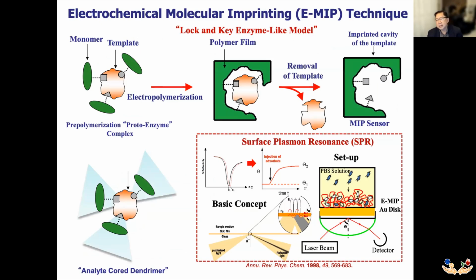And so we've used this effect to design sensors. These films can be prepared on surfaces that include a surface plasmon resonance spectrometer, an electrode surface, or even an electrochemical impedance spectroscopy working electrode. So in this case, you prepare a substrate or your analyte, surround it with monomers that we actually studied in terms of their particular electropolymerizability. Electropolymerize the complex, which leaves you this templated structure. And by removal of the substrate or chemical, you're left with a cavity that is very specific to the original template. So using this principle of MIP or electropolymerized MIP, we were able to design sensors that have high sensitivity